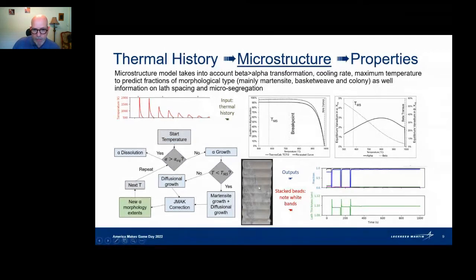The point is that with his models, he was able to predict the occurrence of these small banding regions throughout the build of the layers. And again, based on the thermal history that each layer saw as the build was progressing.